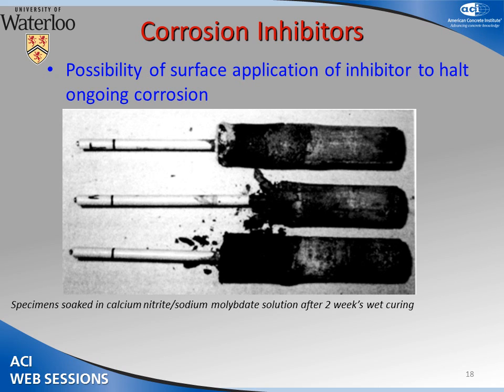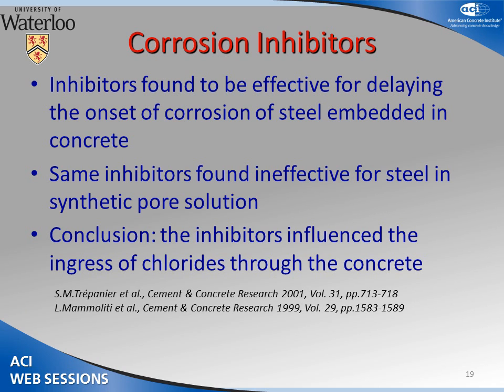Not such a great idea. The other aspects that he looked at were that he, or he and his students, found that the inhibitors were very effective in delaying the onset of corrosion when the concrete was exposed to chlorides from the outside.